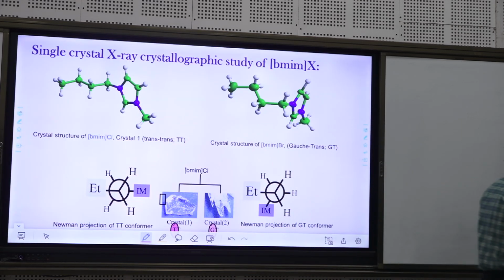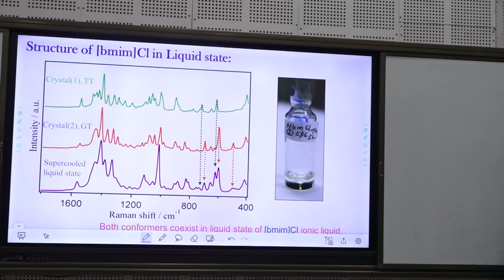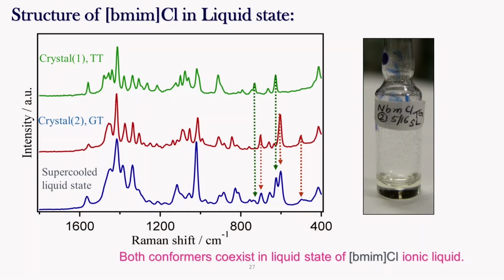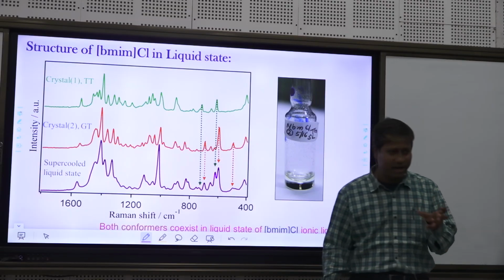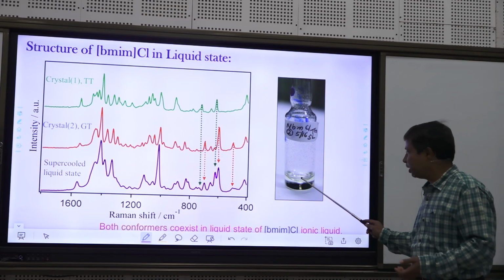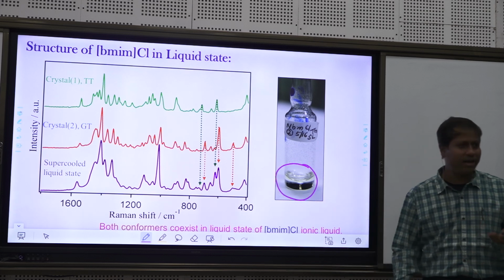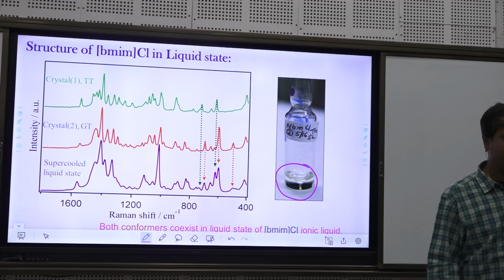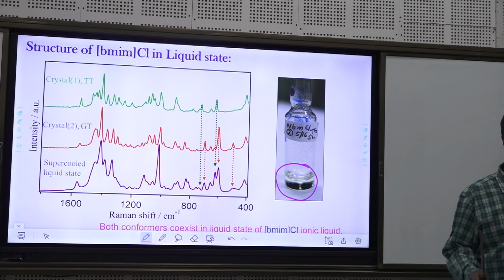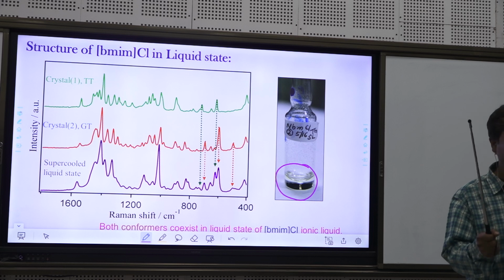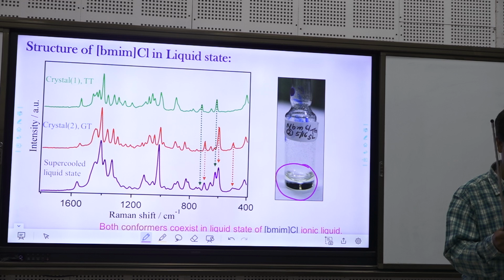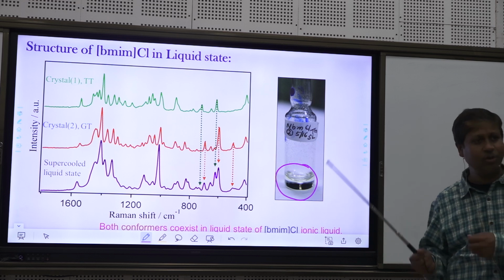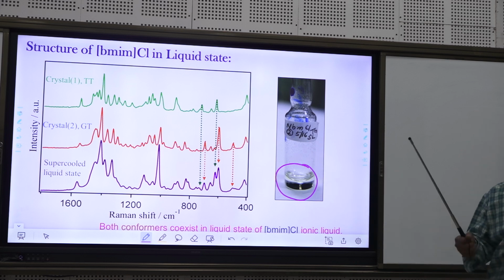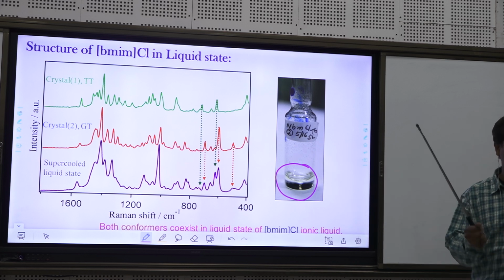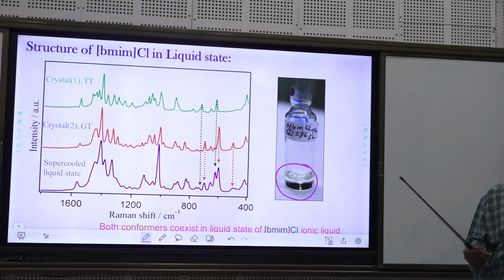This one in fact was the first observation which says that ionic liquid can have polymorphism. So what is the importance of this polymorphism? Polymorphism means that in the ionic liquid, in the liquid, you can have multiple conformations. And if there are multiple conformations, then obviously it will be difficult for them to crystallize or solidify. So we proposed that this might be one of the reasons why such molecules have a low melting point, because they cannot crystallize or solidify as molecules with multiple conformations are there in the system.